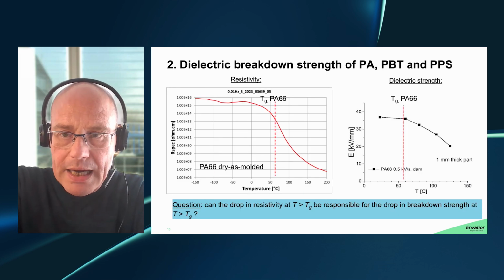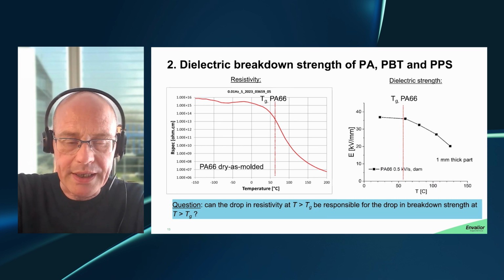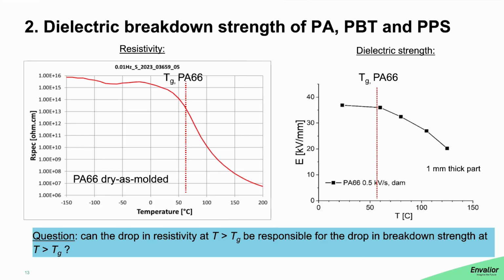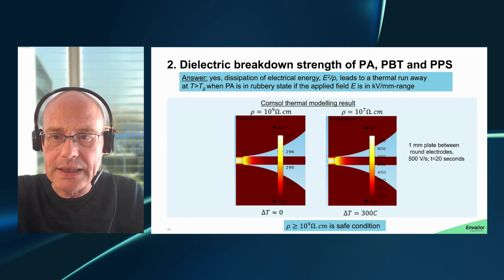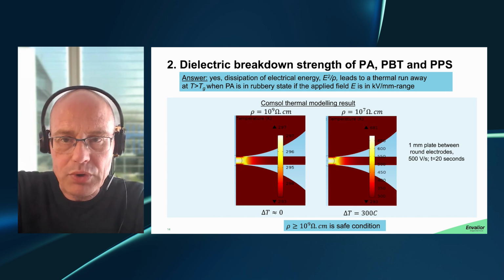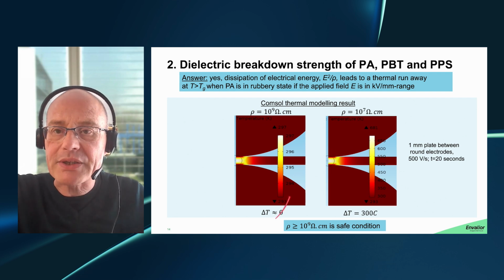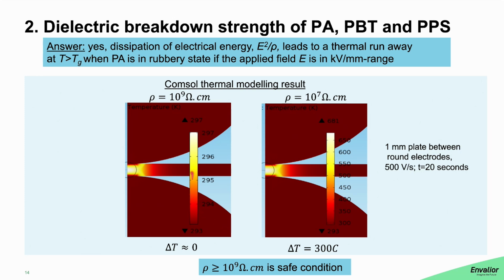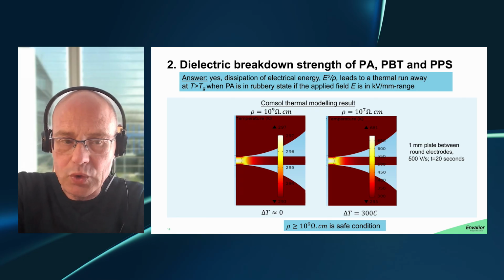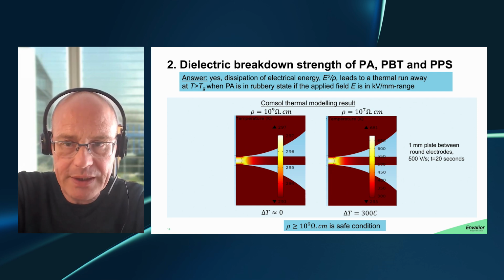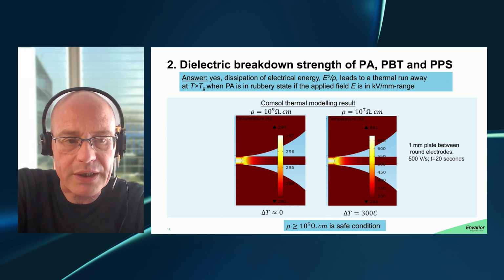So to pose the question more precisely, what we basically looked at is whether these drops in resistivity that we just discussed in the previous paragraphs, displayed on the left, can those be responsible for the drop in the breakdown strength as displayed on the right? That was the precise question we tried to answer. And we did that via a COMSOL thermal modeling calculation. What you see in this picture is a part of an electrode and another electrode, and then you see a plate of polymer in between, 1 millimeter thickness. And to the polymer plate was assigned a specific resistivity. For the calculation on the left, it was 10 to the power 9 ohms times centimeter.